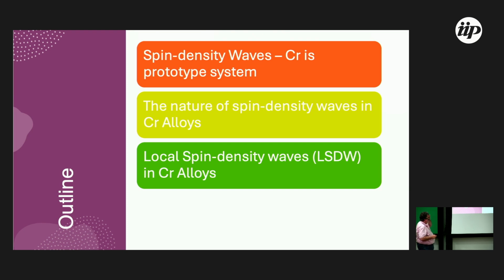The nature of the spin density wave in chromium alloys is interesting because of the change made to chromium to produce alloys. For example, the other transition metals like vanadium, titanium, niobium change the Fermi level of the system. Vanadium, the special case discussed here, has the same structure as chromium. It's a BCC, on the left side of the table, with only one difference, one column less. And I show that this simple change in chromium produces a particular phenomenon, the local spin density wave in chromium alloys.